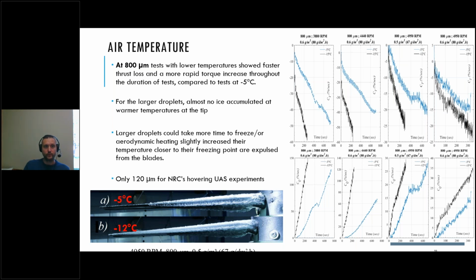When we looked at the results for the 800 micron test, we saw that at lower temperatures, the degradation of the thrust was far more rapid, and also the torque increased more rapidly. You can see on the plots here the blue line for the -5, while the black line for the -12, showing the higher degradation. And what we observed during post-treatment is that for the larger droplets, almost no ice accumulated at warmer temperatures at the tip. If you look at the pictures there, at -5, there's almost no ice at the tip towards the last third of the blade as compared to -12 Celsius degrees.